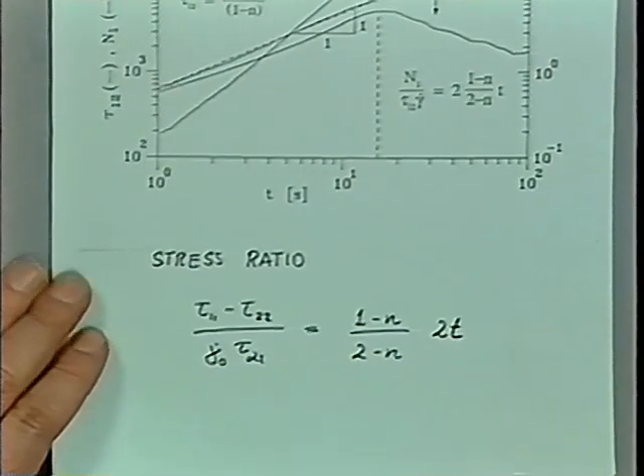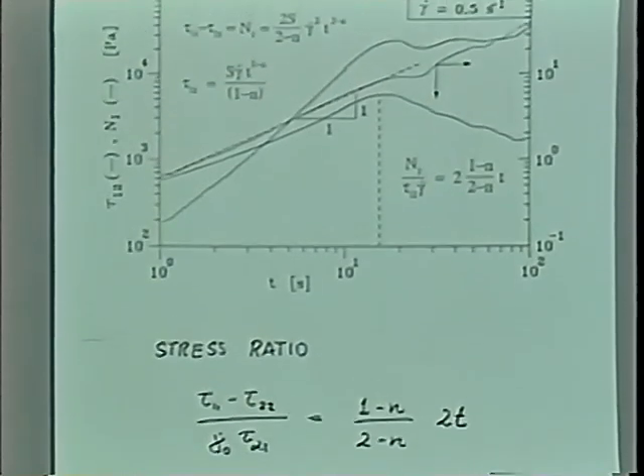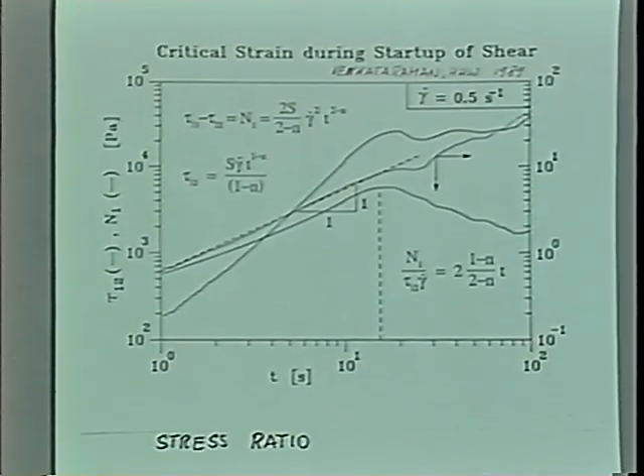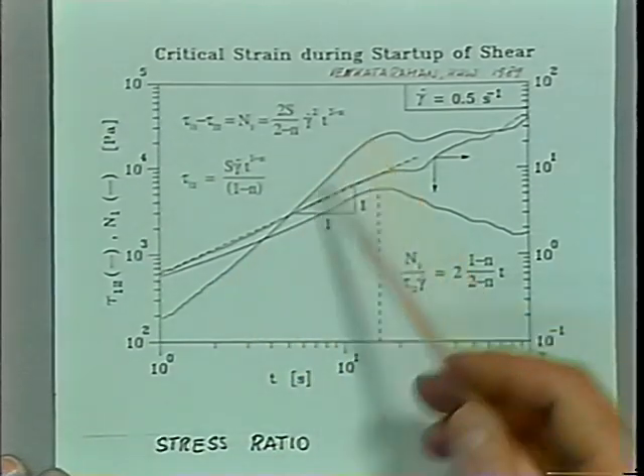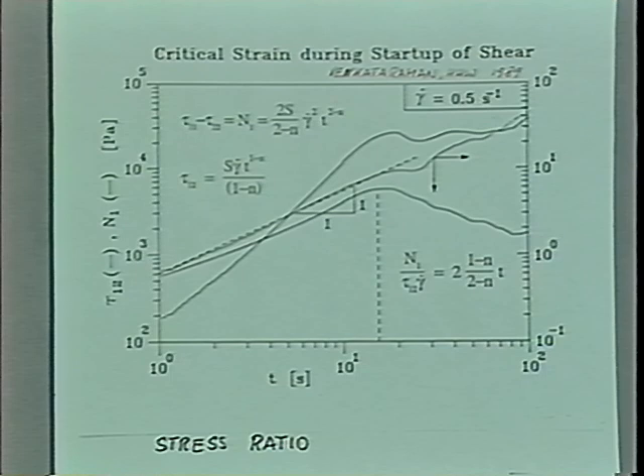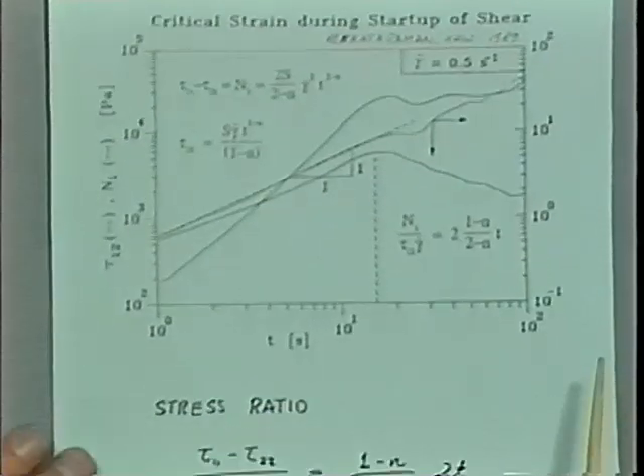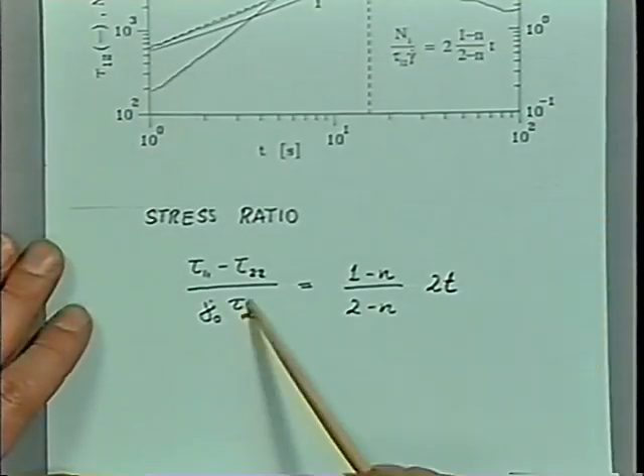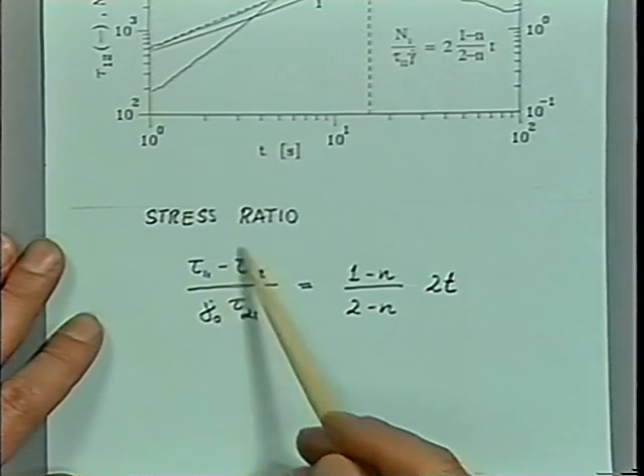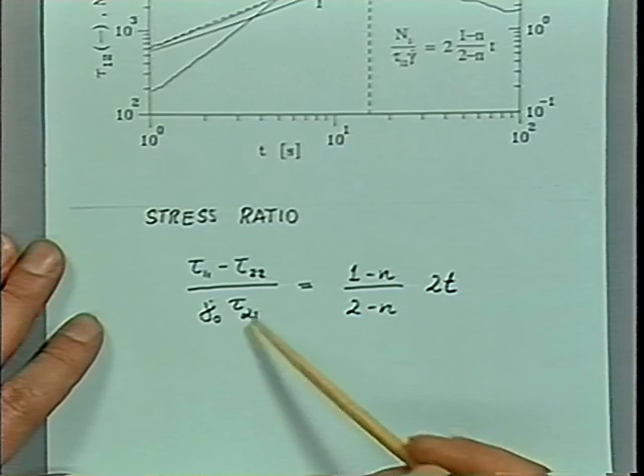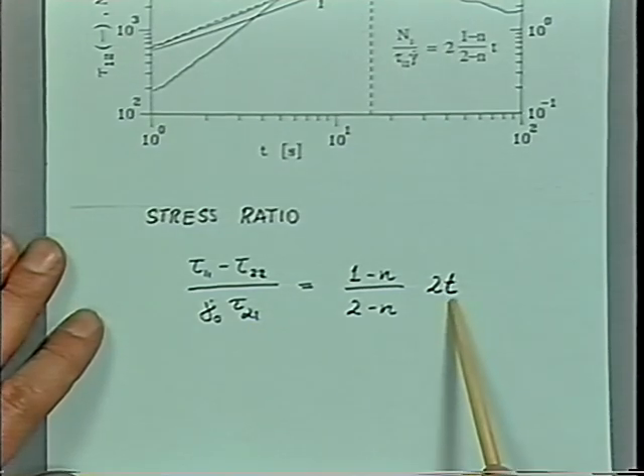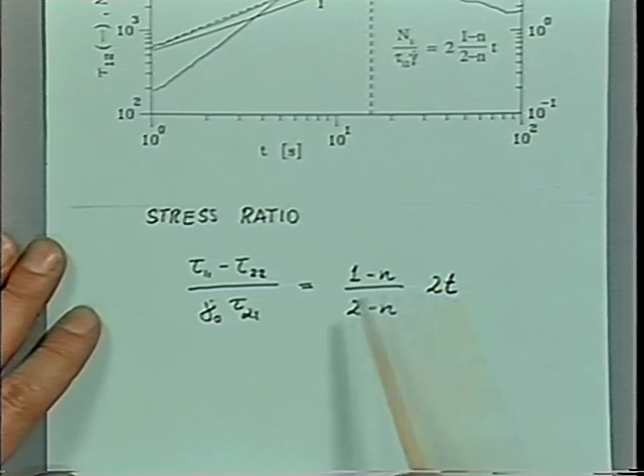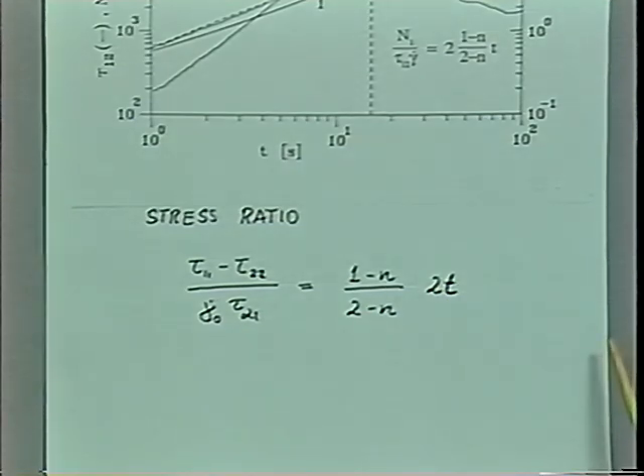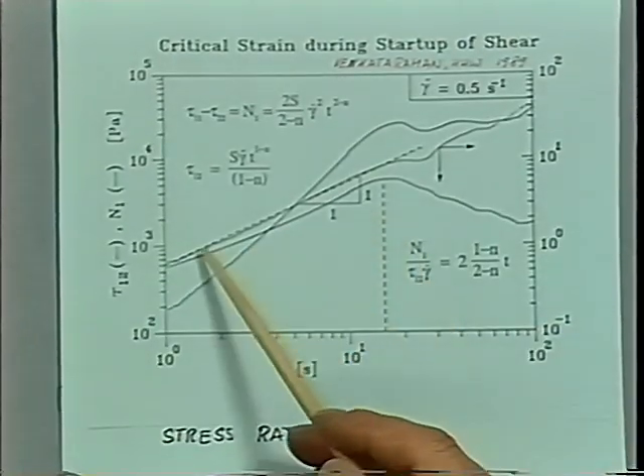Now we wanted to check that. Sundar Venkataraman produced some samples near the gel point and measured the startup of the shear stress and the first normal stress difference. And you can see data here. This is a PDMS material, 10,000 molecular weight, close to the gel point. He measured this individually, but if you take the solution we had before for the shear stress and the solution for the first normal stress difference, and you just take the ratio of the two, then you can see that they just change by t to the power 1. So the ratio should be just proportional to the time t. And indeed, that's what he finds in his experiments.